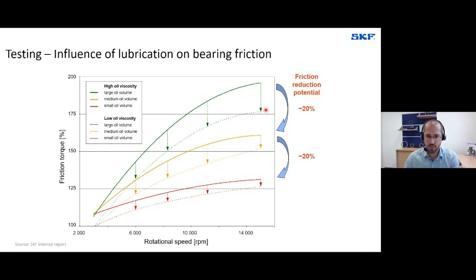And it comes with a side effect, which maybe is not really beneficial for steel bearings. If you go down in viscosity and oil volume, you reduce the lubricant film thickness. You maybe go from a full film lubrication to a mixed lubrication regime, or even down to a boundary lubrication regime. This is not desired for all steel bearings, as it really can lead to surface fatigue issues. So you don't want to have this condition in a steel bearing.